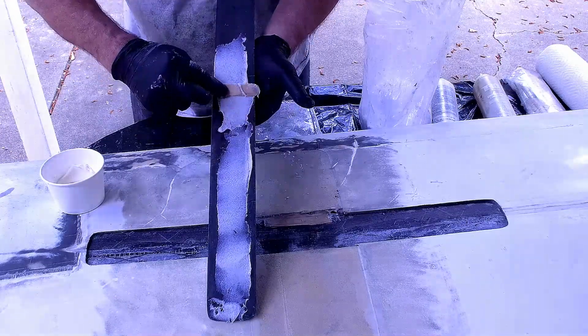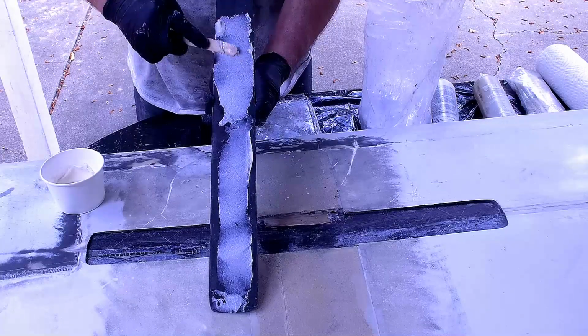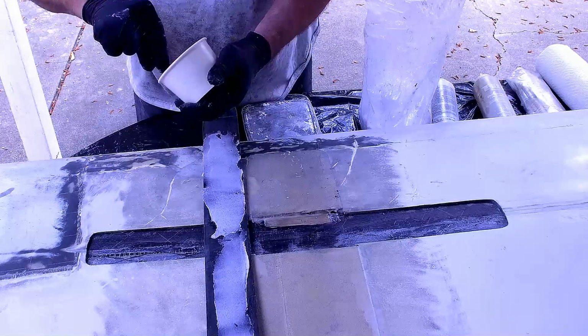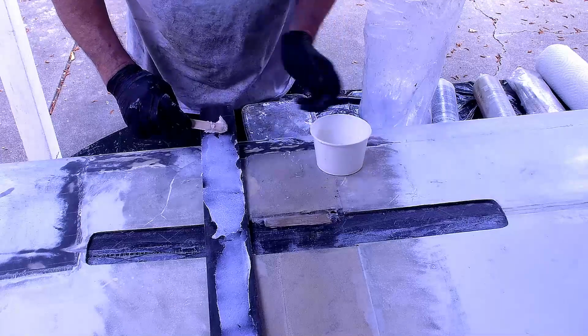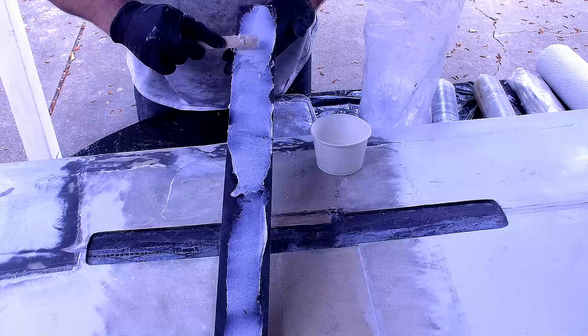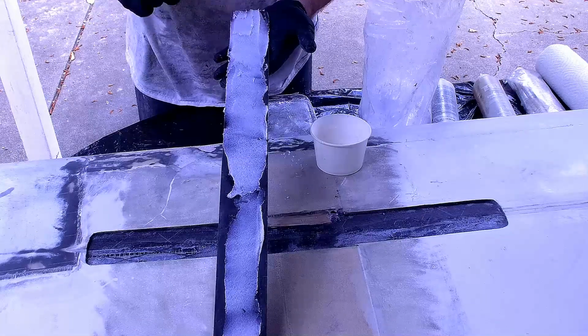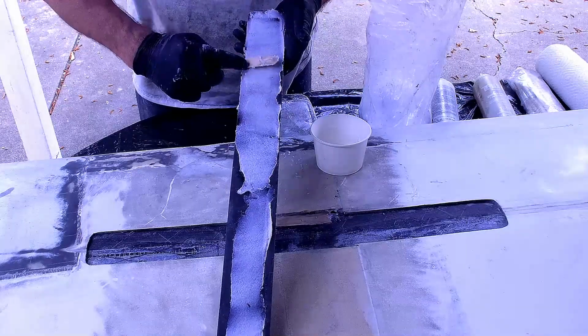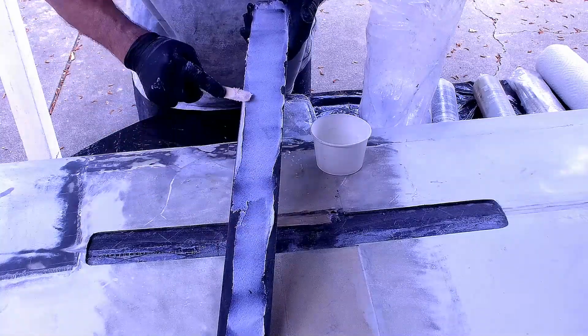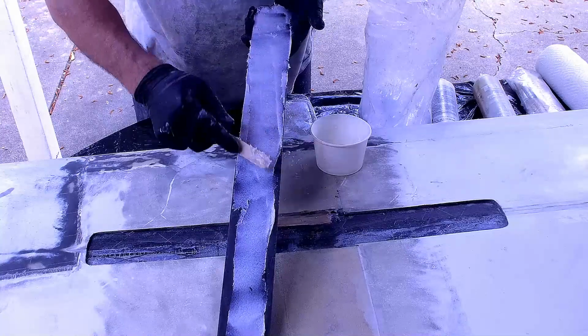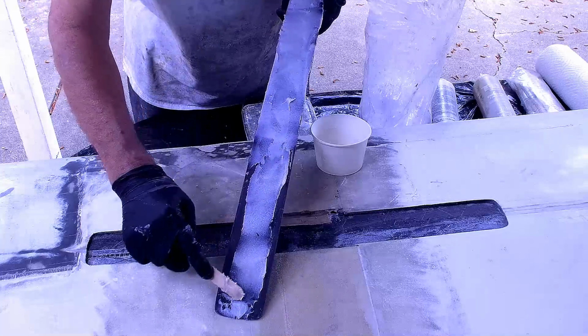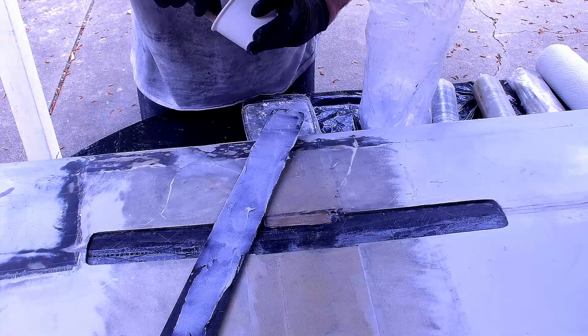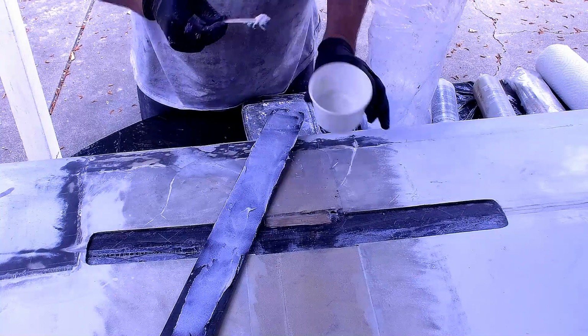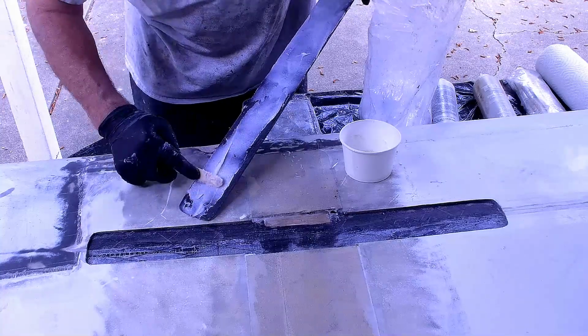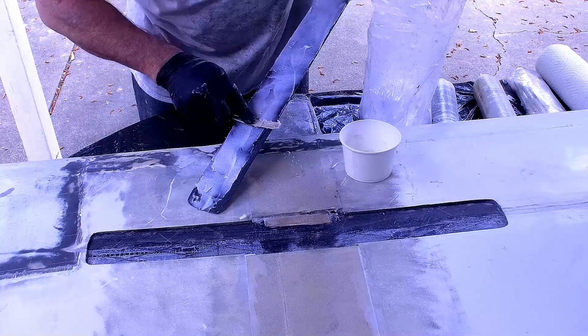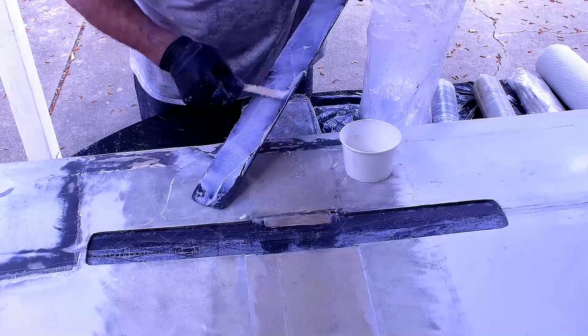What you see me spreading here is a mixture of T88 epoxy. It's a structural adhesive, and I've mixed it with powdered cotton. This mixture is often called flox or cotton epoxy, hence the name flox. Anyway, I am essentially doing what tile layers do, as I'm back buttering the doubler and making sure I get a nice even thin layer on there with no gaps or air holes or anything like that, to make sure that we have the full bond strength available on the spar. And then I'm going to proceed and apply the same adhesive to the spar itself, and then I'm going to compress that spar in there with my weight and let the excess ooze out to make sure that we have a complete bond on every square inch that's available, no air gaps, no spaces, and ensure that it will take the full load.